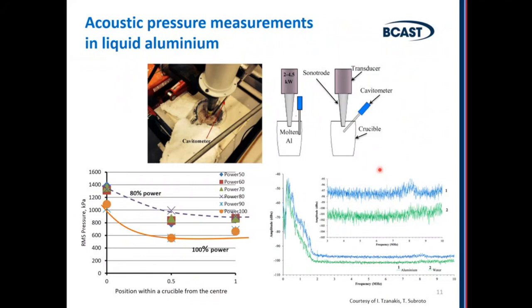So we can not only observe the cavitation in different liquids, but also can measure acoustic pressures using cavitometers. It's a special device which transforms mechanical vibrations of the probe into an electrical signal, and then this electrical signal can be converted using fast Fourier transformation into the spectrum. And then also calibrate it to the real pressures. So we can do it in water.